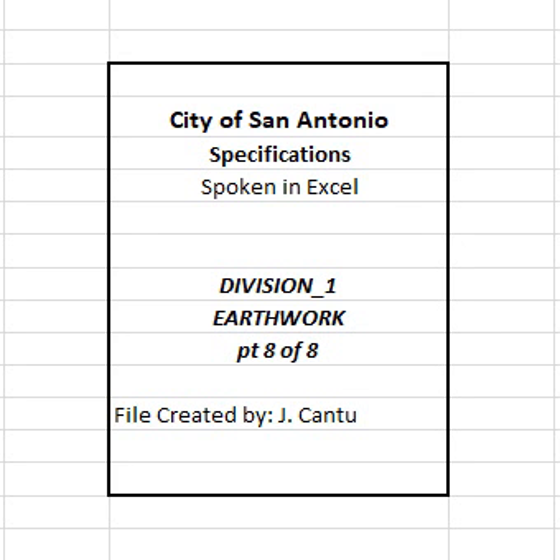Compact to at least 95% of the maximum density determined in accordance with TxDOT Standard Laboratory Test Procedure Tex-120-E at a frequency of 1 test performed per 300 linear feet of paving for 2 lanes. The engineer will determine roadway density in accordance with TxDOT Standard Laboratory Test Procedure Tex-115-E and, if shown on the plans, will verify strength in accordance with TxDOT Standard Laboratory Test Procedure Tex-120-E.